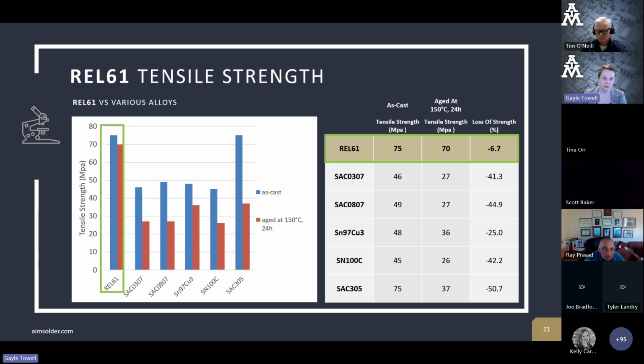But then you age them for a day at 150 Celsius. And what happens? REL61 goes from a tensile strength of 75 down to 70, barely a drop. SAC305, on the other hand, let me get my laser pointer out here. SAC305, which started at 75, essentially cuts in half. And all the other alloys in this test drop rather significantly in aging.